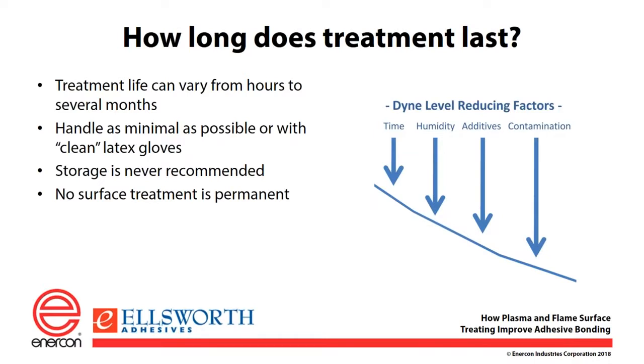So, for instance, let's say we started with a material that was at 30 Dyne and I treated it with a blown ion and it went up to 60 Dyne. It may stay at 60 Dyne for 12 hours and then it's going to start to fall off. It usually never gets back to its original steady state of 30 Dyne, but it will fall off at some point. And that's why we need to work together to try to figure out, okay, I need to be at above 55 Dyne in order to have a good bond. So we'll treat it to a certain level and let you know, okay, I need to do my next step within so many minutes or seconds or hours from the pre-treatment in order to, again, make sure that you get the best bond that you have.